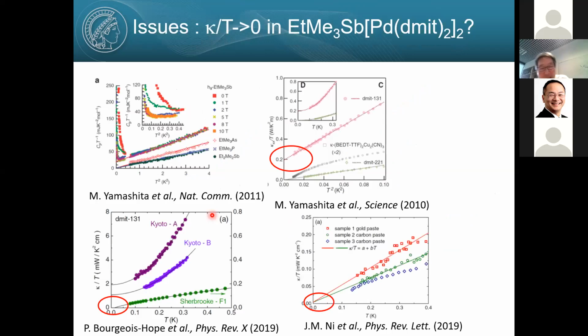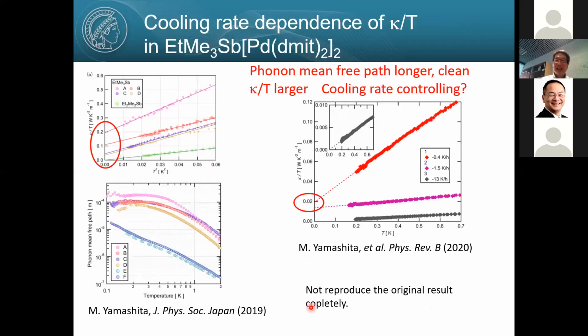And recently, an even more serious experimental issue was related to this beautiful organic spin-1/2 triangular system. So this is the original work, showing T-linear thermal conductivity. Recently, 3 groups, including the original group, measured the same material again, and they didn't reproduce this result, and thermal conductivity divided by T goes to 0. So that means you don't have mobile excitations. Okay, and if they don't move, we are in big trouble. So we don't know what it is.